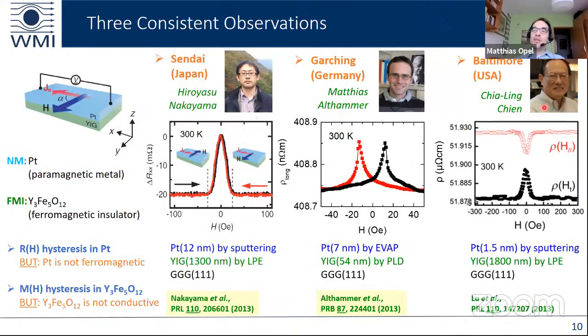result was also seen by a third group at that time in Baltimore. The three samples were more or less the same. They consisted of a platinum top electrode on a YIG thick film, in this case 1300 nanometers, a thin film in our case 54 nanometers, another thick film here, and on GGG substrate. And these three groups saw consistent observations. So why do we see this magnetoresistance?